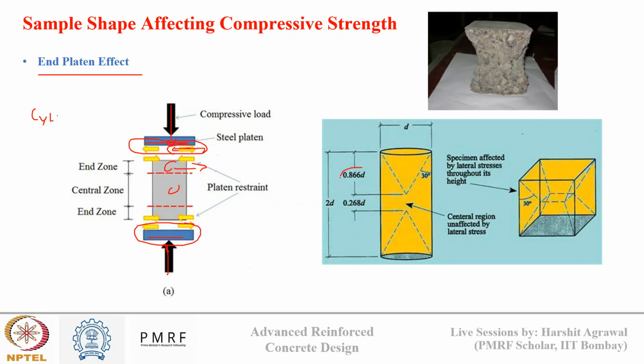generally it resists up to a depth of 0.866 times the diameter of the sample. Now for a cube, the half-height is 0.5d, and this 0.866d is more than 0.5d. So you see this end platen effect can go up to the entire length of the cube. However, for a cylinder having diameter d and height 2 times the diameter, the end platen effect doesn't correspond to the complete length. So you see here in the cube, it corresponds to the complete depth of the cube. However, for the cylinder, there is a weak zone in between where there is no end platen effect and there is just this tensile effect that is generated by the compression load.